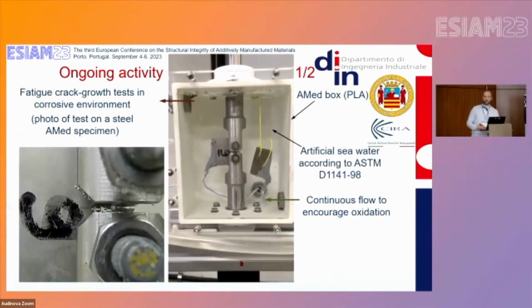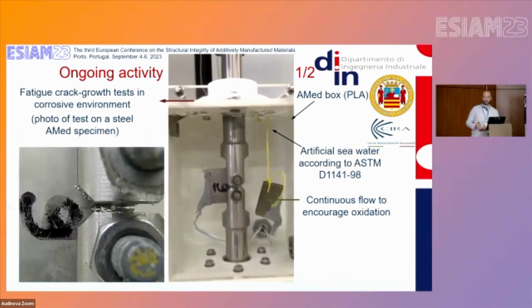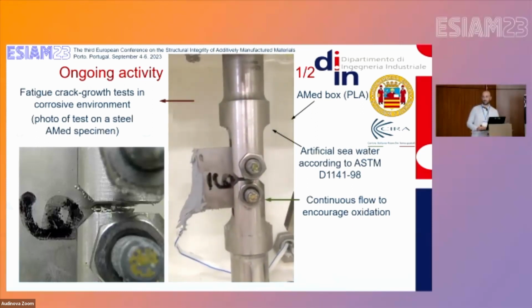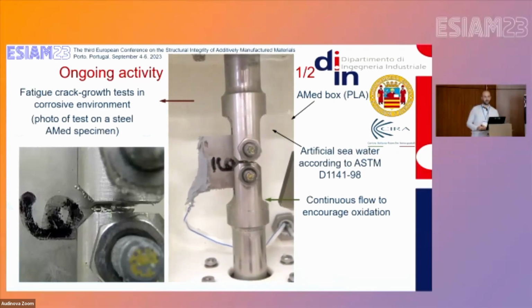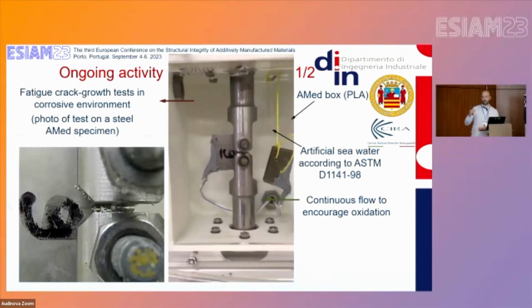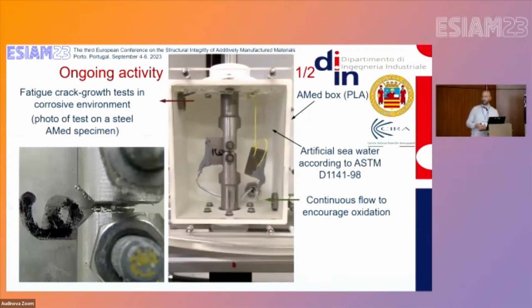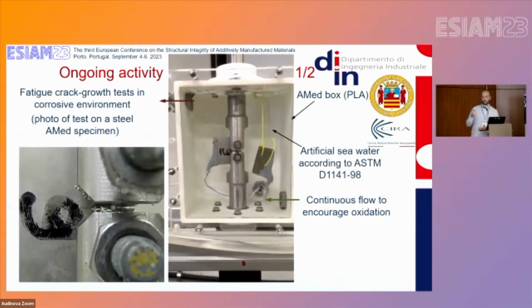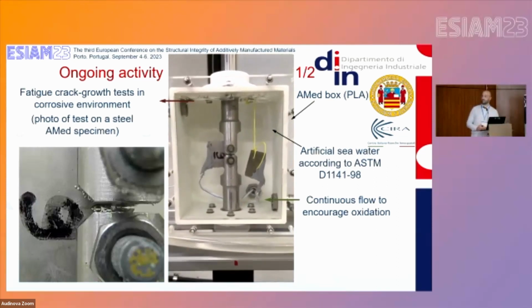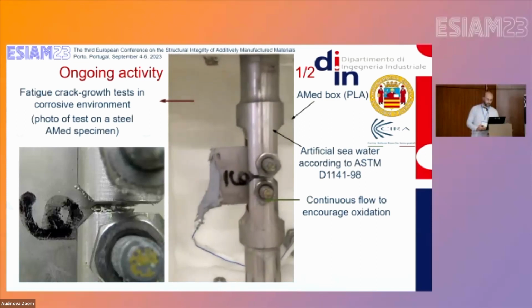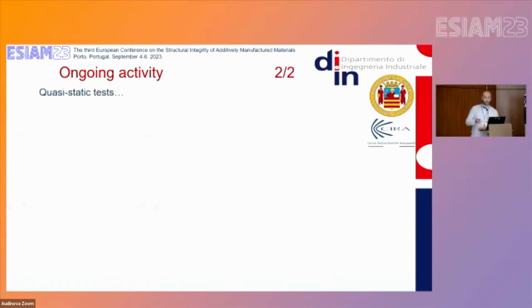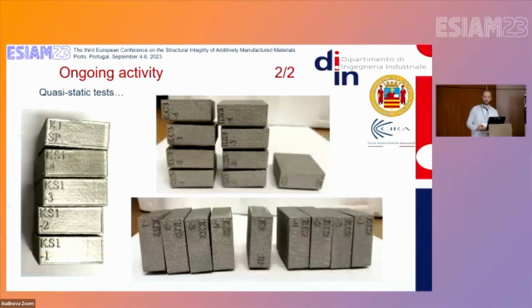The water is continuously flowing through a pipeline during the test. The specimens were kept in seawater for 24 hours before the test, and then the test was continued inside the chamber with the water continuously rotating, moving around the specimen. This is another activity that we are doing, the quasi-static tests. These are simply some photographs of the samples that were manufactured and need to be machined to be tested in quasi-static conditions according to the standards.